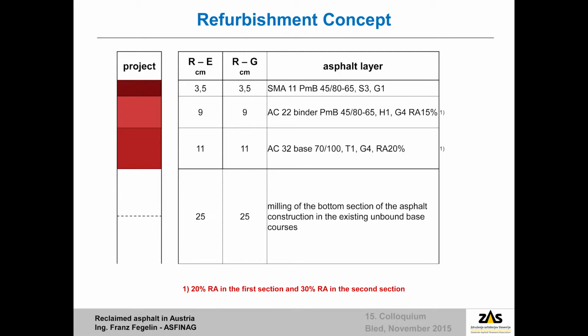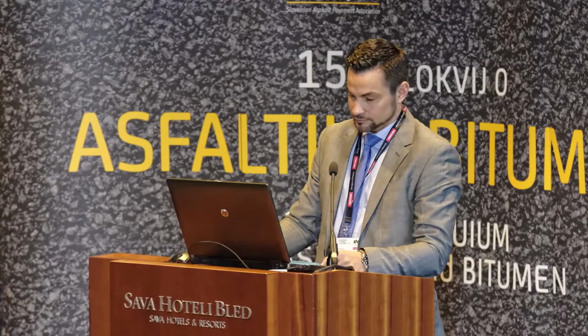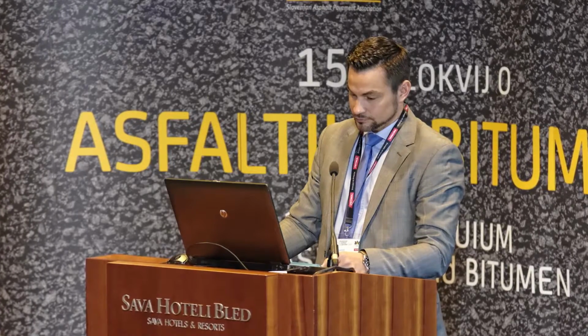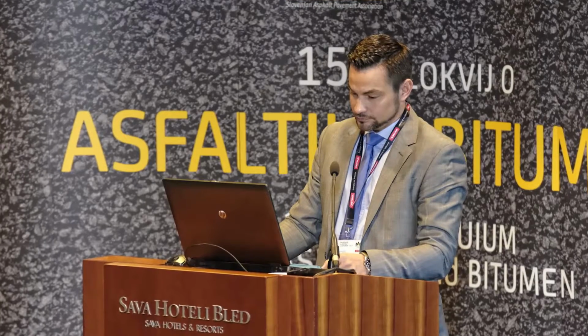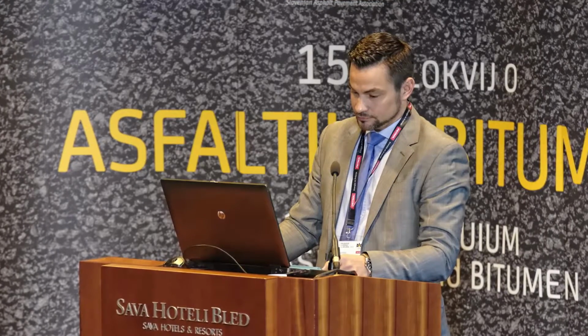As you can see, these ramps have been refurbished more than once, so we had really enough material to be reused. The layering design of the ramps was planned as shown in this table. To get the material, we milled layer by layer. The rest of the material we didn't need was processed and included in the unbound base courses in order to improve the quality.